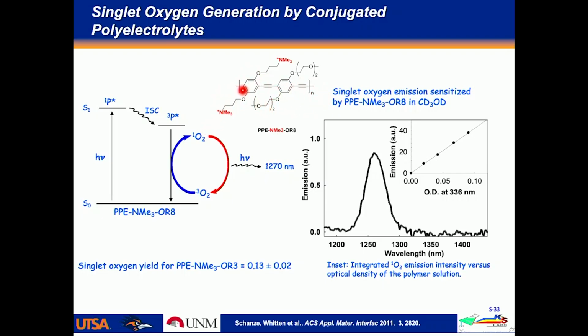And when we irradiate the polyelectrolyte, we create an excited singlet. It undergoes intersystem crossing to a triplet. And that triplet then can react with ground state oxygen to produce singlet oxygen. And we can detect that by the emission that occurs in the near infrared. And so we can measure the oxygen that's produced, the singlet oxygen, and quantify it with a quantum yield.